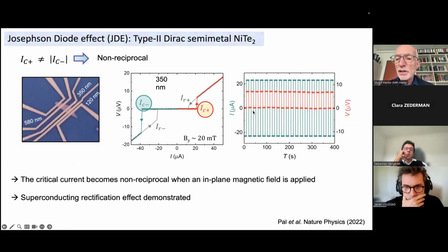But you see the red curve on the right-hand side, which is the voltage. And for one direction of the current, the negative direction, it's 0. But for the positive direction of current, it's a finite value. So we have built a diode, a superconducting diode or Josephson diode with an extraordinarily large diode efficiency. As I said, here it's 40%, but for a narrow spacing, it's up to 80%. And we only see this rectification effect in the presence of this small magnetic field. And I didn't mention, but these experiments are carried out at approximately 10 millikelvin in a dilution refrigerator. So this is a wonderful effect, a huge giant diode effect.